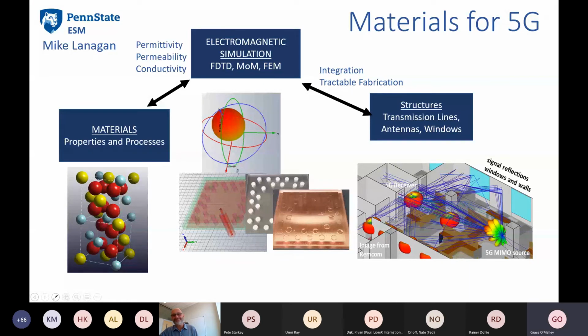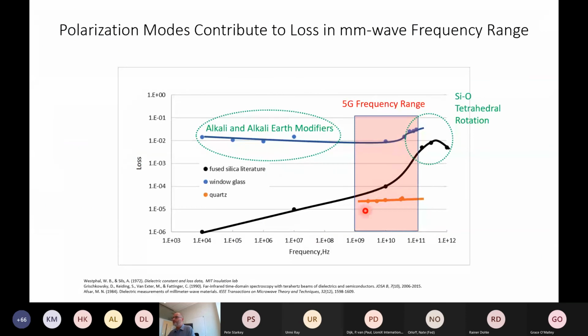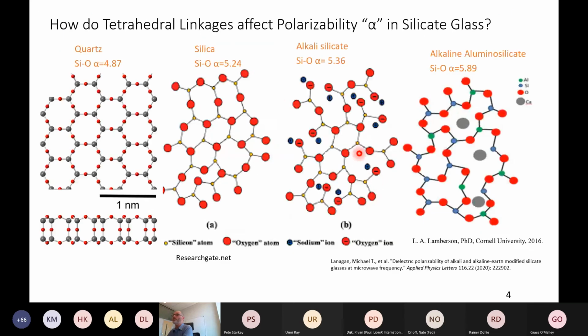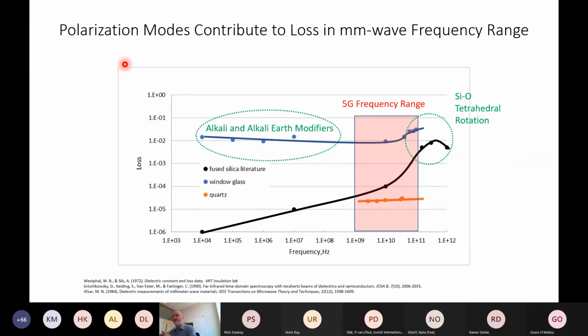I'm going to take two shorter questions first, and one is how would you explain the difference between the fused silica and quartz DF in the gigahertz range? All right, so the quartz itself is crystalline. What happens is there's no real degree of freedom. Basically, the structure is really locked, and so there's less opportunity for the ions to move, and so they don't create a loss. And then if you look here at the fused silica, because it's a more open structure, it has extra movement, and that's captured in this polarizability term here. That is just the way the materials are, and that's what we're given from nature, this extra freedom with the glass structure.